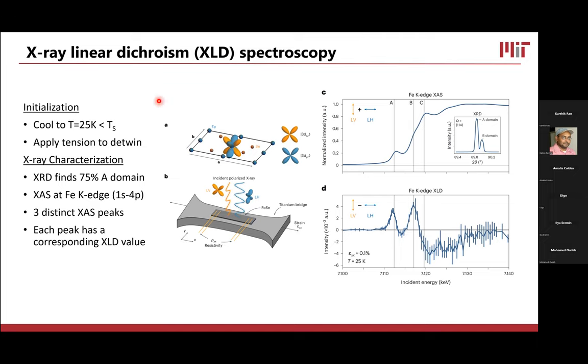So to initialize the sample, we cooled it down under zero strain to 25 Kelvin, which is below the nematic transition. And then we applied enough tension to partially detwin it. Then we did our X-ray measurements. From X-ray diffraction, we found that in this particular strain state, we had 75% A domain, which is the tensile favored domain, and 25% B domain. So this inset figure shows you that. This is essentially a line cut at one particular temperature and strain that shows that we've partially detwinned the sample. Then we can do X-ray absorption spectroscopy.